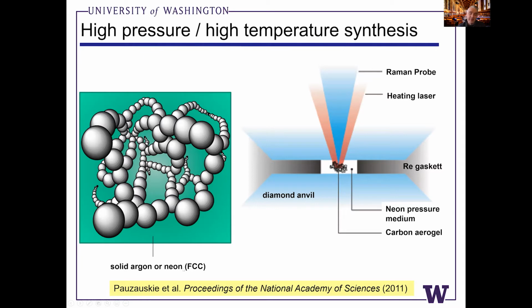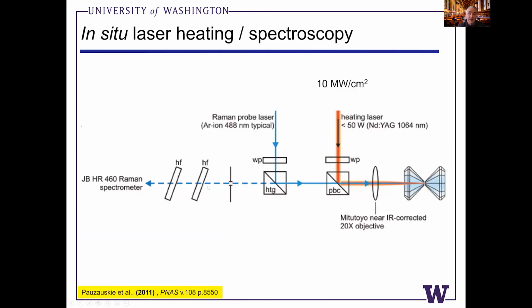Argon will freeze into a face-centered cubic crystal structure that's chemically inert, or at least we thought it was completely chemically inert previously, and it's optically transparent. So once we fill the amorphous carbon aerogel, we laser heat it with a really high intensity, high irradiance fiber laser. This is either a neodymium YAG laser or a ytterbium fiber laser through the windows. We can also focus Raman lasers to do spectroscopy of these materials in situ.